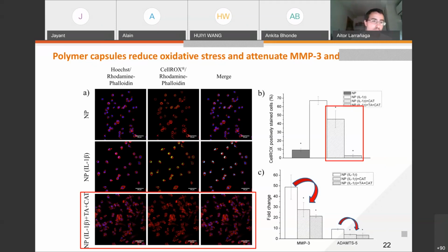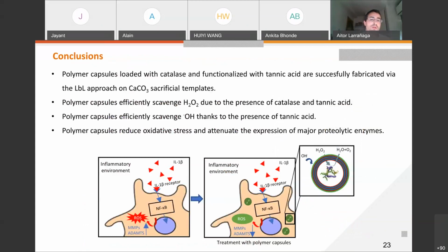So from this work, we can conclude that polymer capsules loaded with catalase and functionalized with tannic acid can be successfully fabricated via the layer-by-layer approach by using calcium carbonate sacrificial templates. These polymer capsules, remember, were able to scavenge hydrogen peroxide and hydroxyl radicals thanks to the presence of the encapsulated catalase and the surface functionalization with tannic acid, respectively.